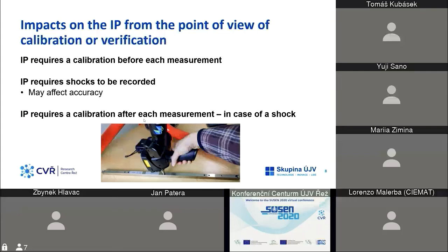Point of view of calibration or verification. There is a requirement of calibration before each measurement. This calibration is performed on an 800 millimeter long checking rod that you can see in the picture. There is also some kind of difference, but this is not so important. There is also a requirement for shocks to be recorded, because these shocks may affect accuracy, and these shocks are recorded by a simple accelerometer. And in case of shock, we have to do calibration also after each measurement.